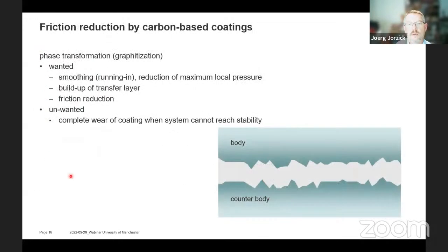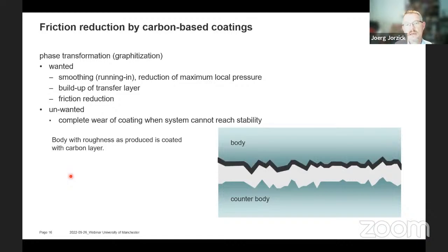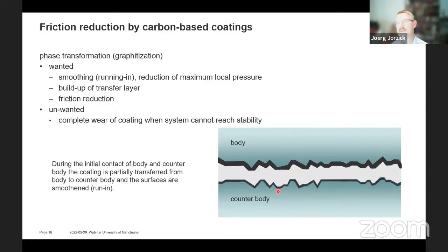So one important thing, especially for the carbon-based coatings, is the so-called running in behavior. If you think about the surface that is coated, and the coating is just following the actual surface, in the initial contact with the counterbody you will have the first contact at the roughness peaks, and there we will have this kind of graphitization, which is first smoothening the tribological system and also transferring a little bit of graphite to the counterpart.